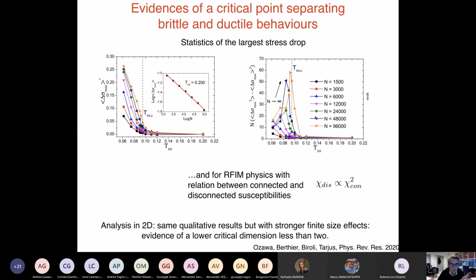What you see here is delta sigma as a function of temperature, for different system sizes. You see that you go from one regime in which delta sigma is different from 0 to a regime in which delta sigma is 0. This is exactly the same thing that I was showing before. Now, the interesting thing is, if you look on the right, these are the fluctuations of the delta sigma max, the statistics of the largest stress drops.